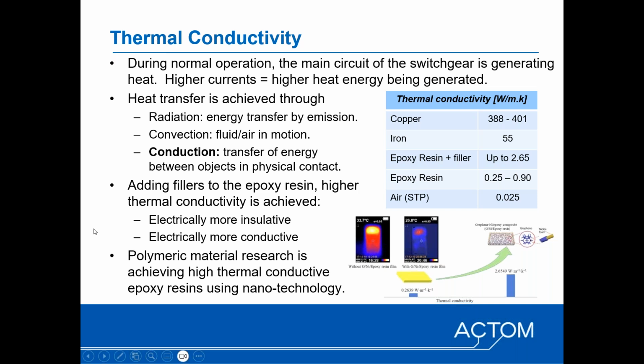Getting the heat from the conductors: by adding additional fillers into the epoxy resin, your thermal conductivity can be changed, and you can actually get up to 10 times the thermal conductivity of your resin by adding these fillers. But by adding specific types of fillers, you're changing the electrical properties of the epoxy as well, to be either more insulative or more conductive. So by selecting the correct fillers, you actually need to create a more insulative epoxy with high thermal conductivity rather than a conductive epoxy. And that's nothing to do with the earth screen layer on the outside. This is the body of the epoxy between the conductors and the earth screen.